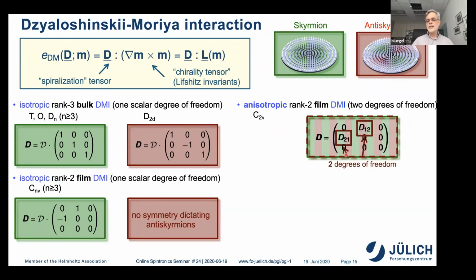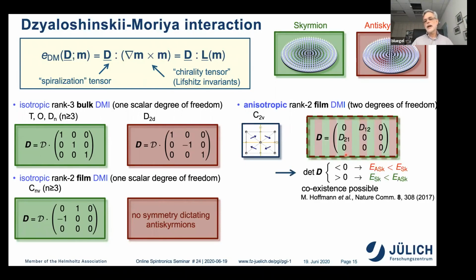And with these independent parameters, you can now have something which is different from the other skyrmions. You can have the antiskyrmion and the skyrmion simultaneously. If your determinant is smaller than 0, the antiskyrmion is more stable and has a lower energy, and if it's positive, the skyrmion has a lower energy. This is different from the antiskyrmion which we have seen in the D2d structure. In the D2d structure, you can only have one type of skyrmion, which is the antiskyrmion. My statement is not fully correct. There you can also have two skyrmions, but one will be a chiral skyrmion and the other one will be a dipolar stabilized skyrmion.